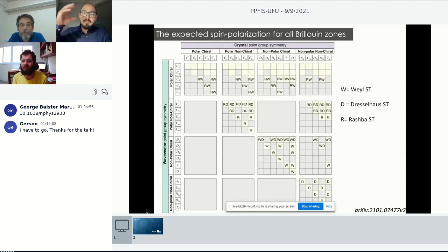So we have a spin splitting in each layer, but because of the total cancellation, it turns out that the spin splitting looks like degenerate bands. We can think that this is a spin splitting on one band, and this is a spin splitting of the other band, and this is up and down, and this is up and down. But if you put the two together, you will have up and down together, degenerate, right? But the degeneracy is between different layers. So this is up and down for different layers, for instance. We can think like this.